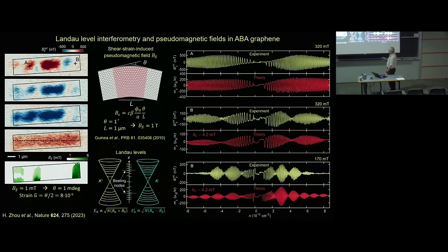So we see pseudomagnetic fields in the range of 1 to 6 millitesla. So this is 5 orders of magnitude smaller than the pseudomagnetic fields that have been previously observed, on the order of 100 Tesla in...